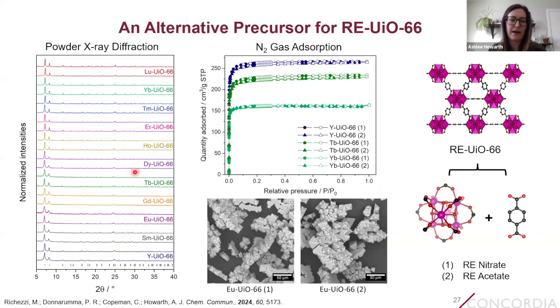So here we have the powder X-ray diffraction patterns showing that we can make all of these different analogs of rare earth UiO-66, whether we use a rare earth nitrate or rare earth acetate precursor. All the materials are crystalline and phase pure and isostructural to each other. So here on this plot, in each case, the bottom trace is the MOF made with the nitrate, and the top trace is the one made with the acetate. So you can see that they're all the same.